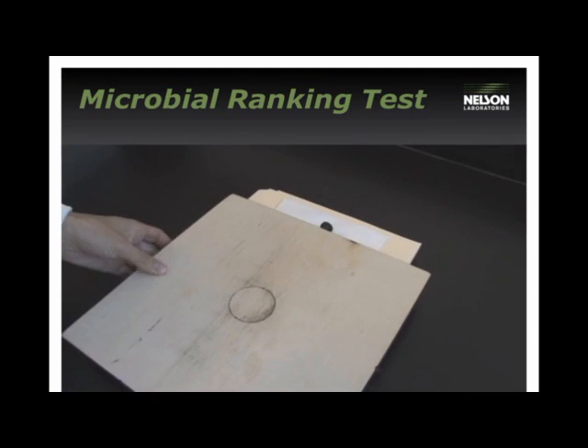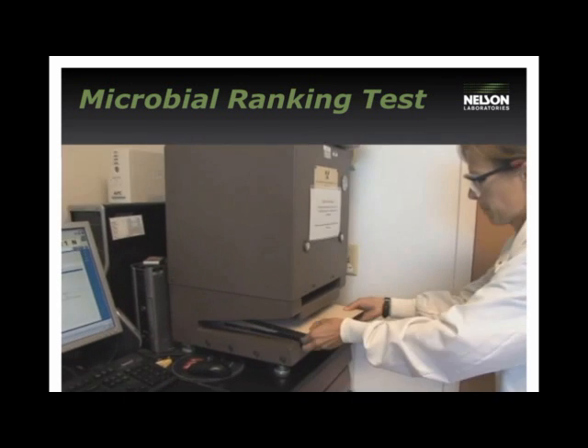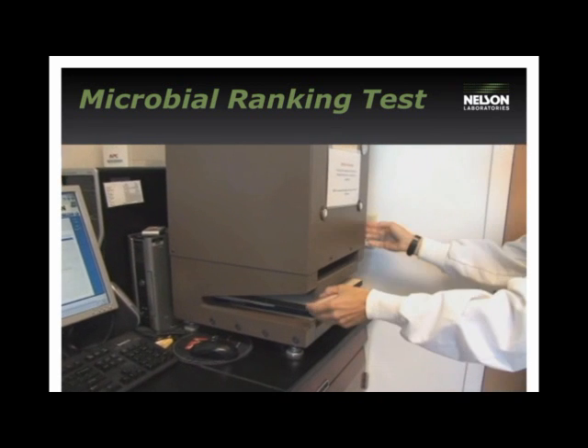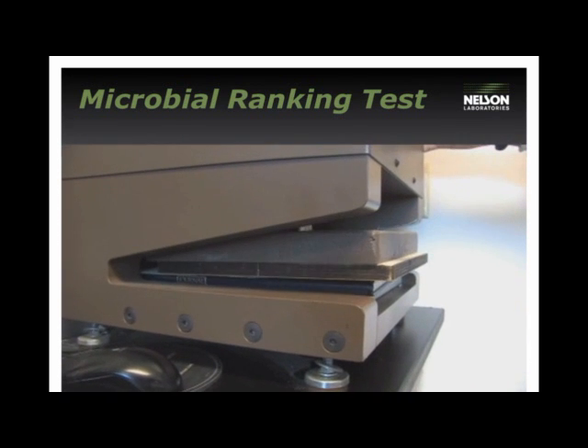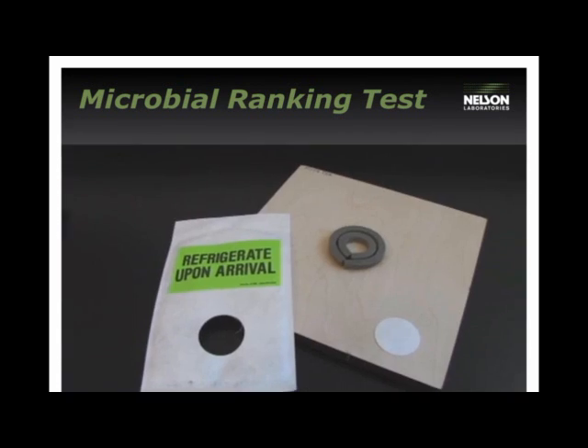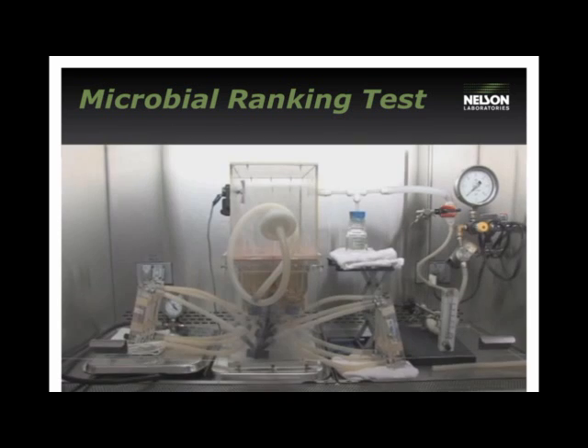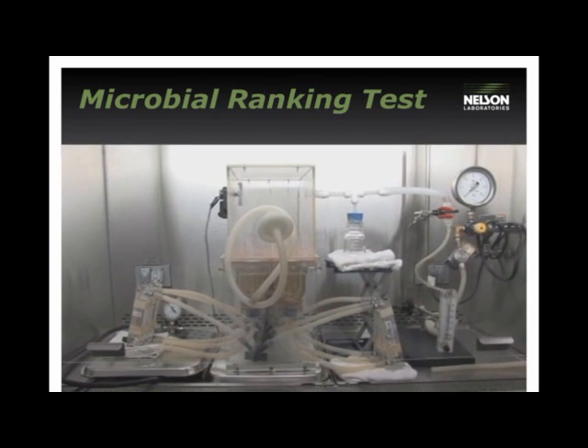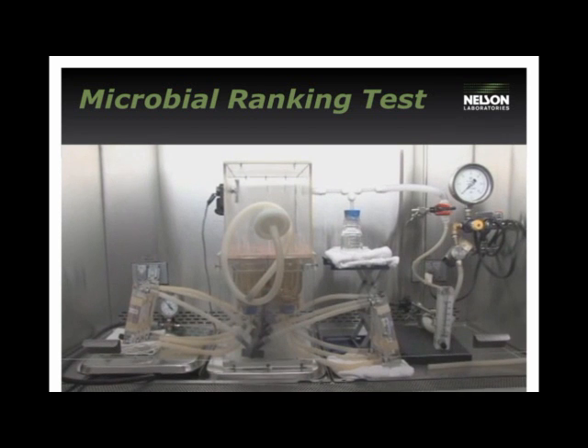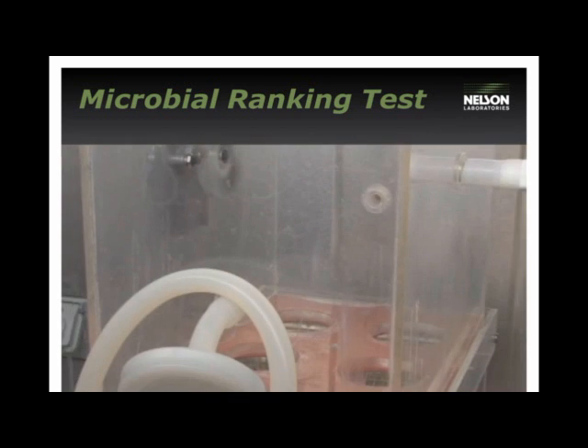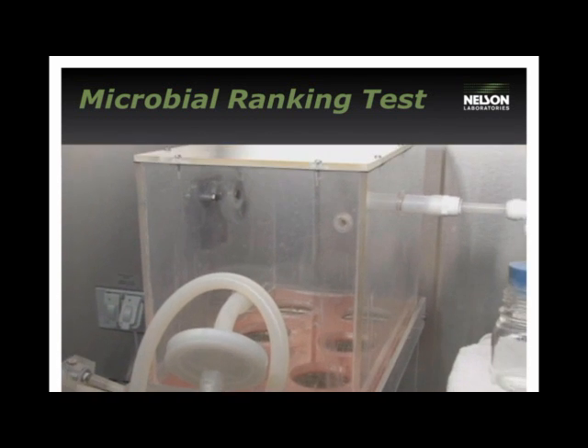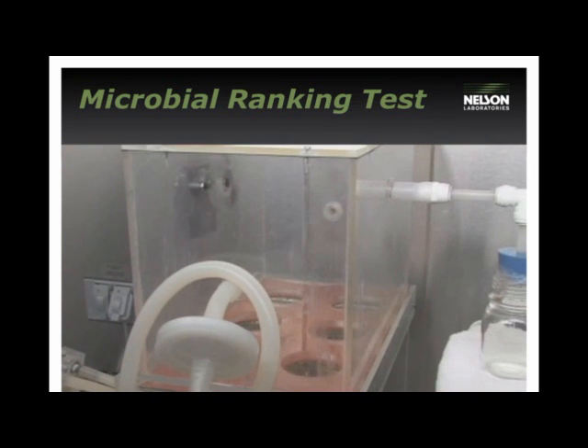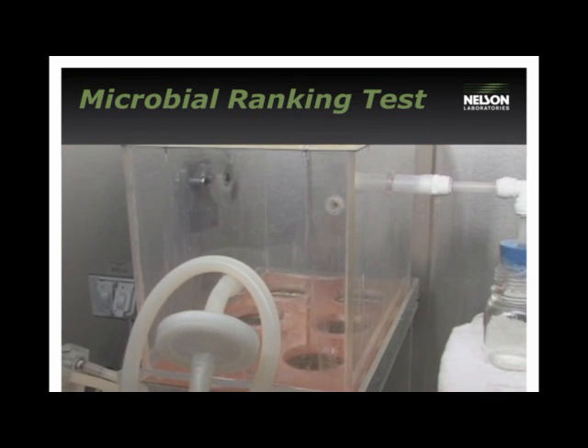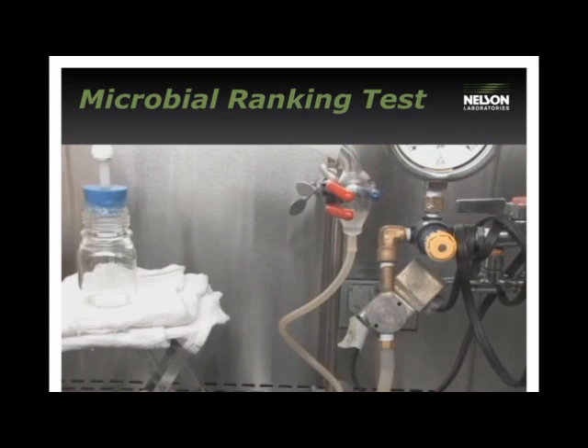Samples are cut into 47 millimeter discs and are usually sterilized prior to testing, both to incorporate any material changes that occur during sterilization and to reduce extraneous bacteria. At least two samples need to be tested of each material per the standard, but the test unit can accommodate up to four samples per run. Positive and negative controls are run in the other two slots.